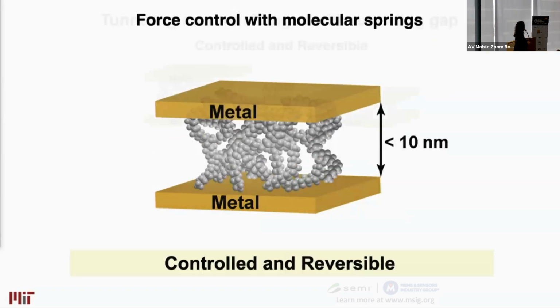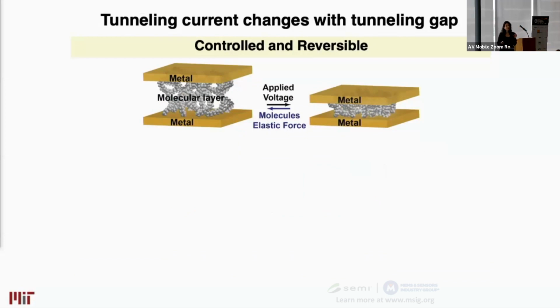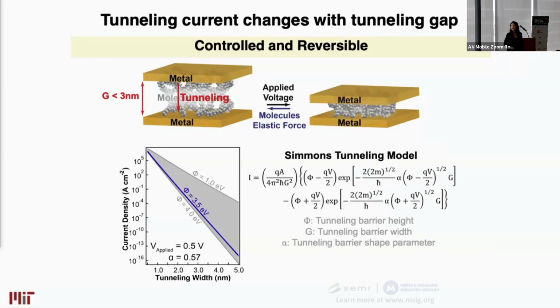So if you make these junctions small enough, and with that I mean less than 3 nanometer in size, then you're going to get conduction through tunneling, quantum tunneling, through these junctions. So you no longer need direct contact between your metal electrodes, but you can get conduction through tunneling. Now, tunneling current changes exponentially as a function of reduction in the tunneling gap. So you can imagine by tuning the gap, now you have a new mechanism for designing electromechanical switches.